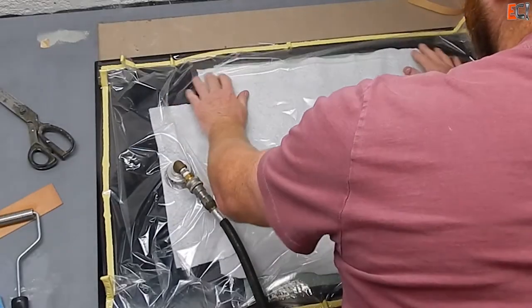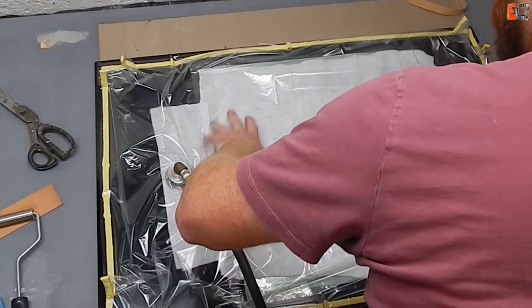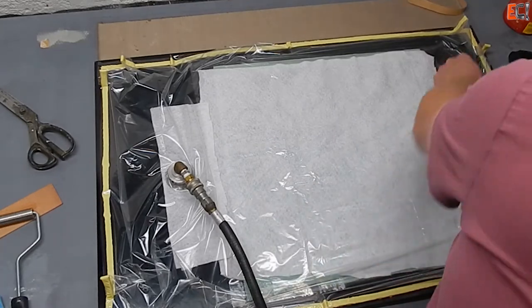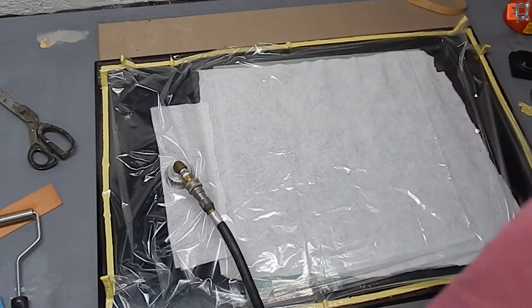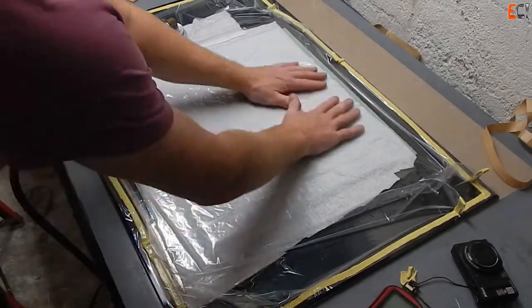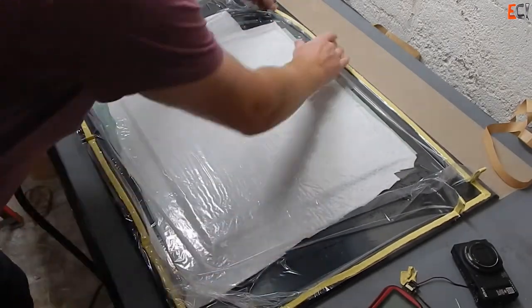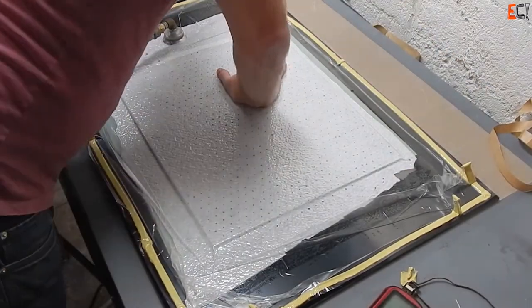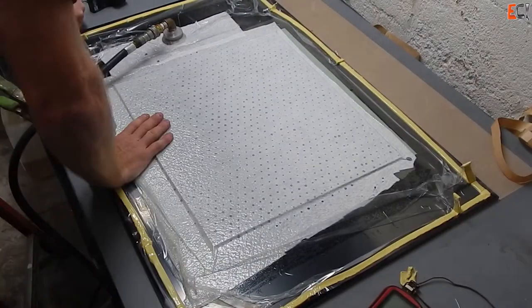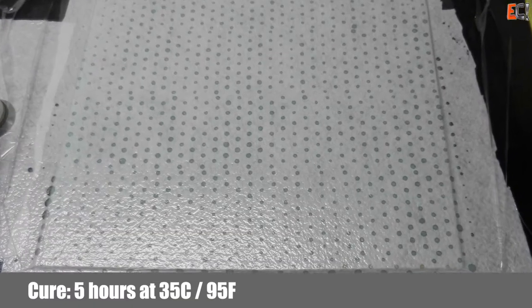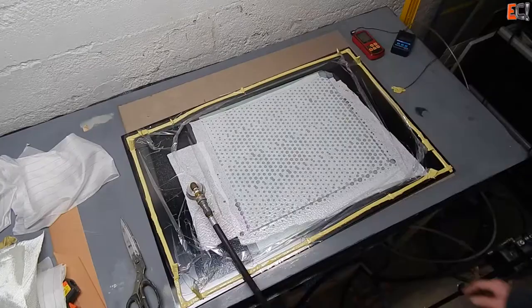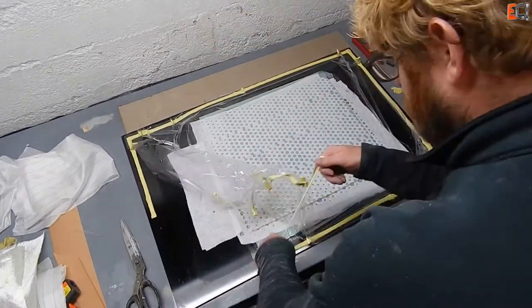And I'm just going to suck it down here. And on this one I'm only going to use about half vacuum. This is about 15 inches of mercury, 500 millibar. So I'm going to work this sealant tape down. I had this bag folded up before I used it and so there are little spots where the sealant tape is not as thick where it was folded over and so it's a pain to chase those down. As I let it cure, there's decent bleed, not too much, and of course the resin can't come up from the bottom so I'm only bleeding out the top skin.